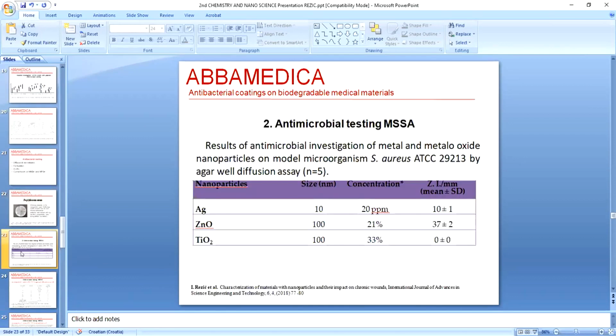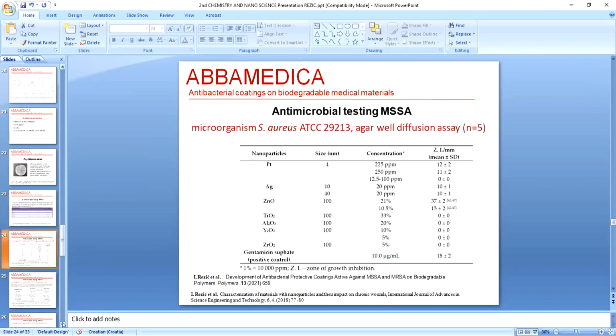methicillin-resistant Staphylococcus aureus and found that small nanoparticles of silver with a size of 10 nanometers are really efficient, as well as zinc oxide. In contrast, titanium dioxide was not efficient against this microorganism. Afterwards, we tested some other oxides, which were also not efficient, but we tried to compare silver of different size, which was also as efficient as the smaller silver nanoparticles. But what is really interesting is that we started also developing surfaces with platinum nanoparticles of only 4 nanometers, of different concentrations, and we were really able to produce interesting antimicrobial effects.